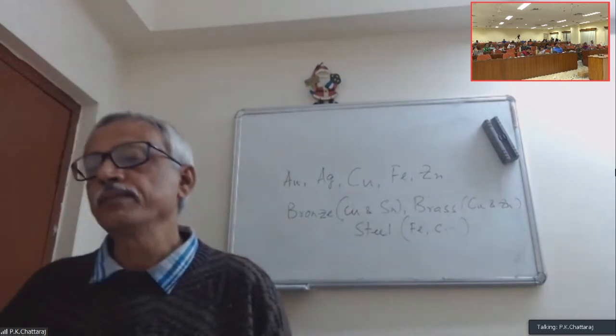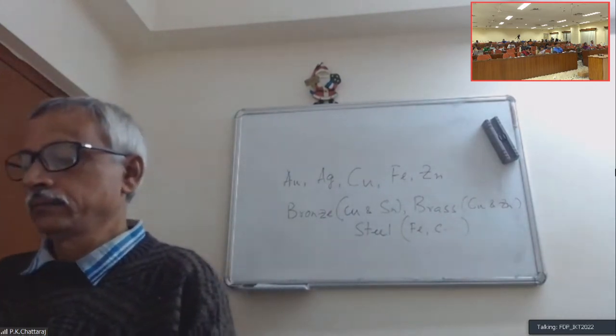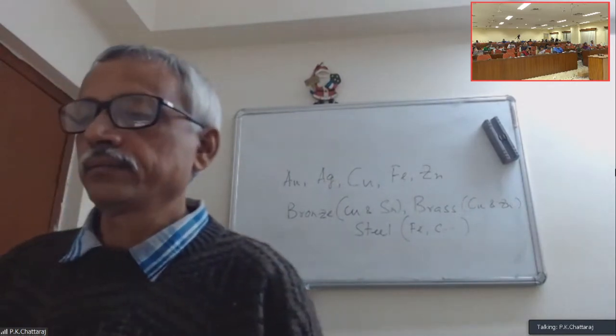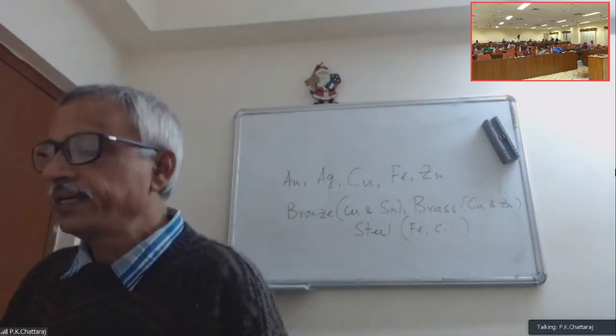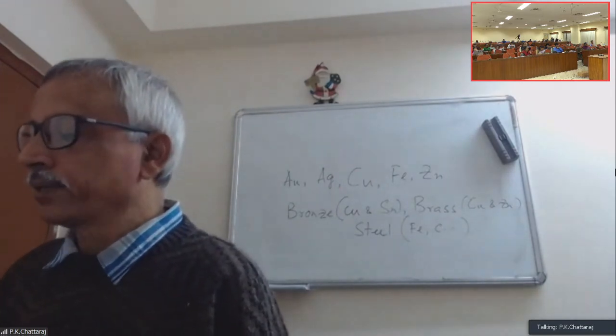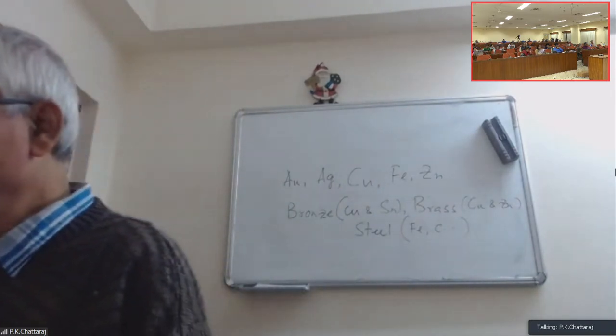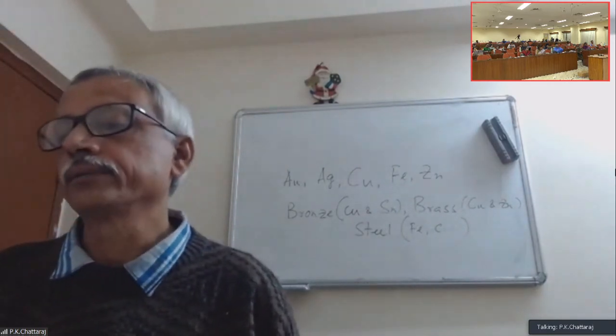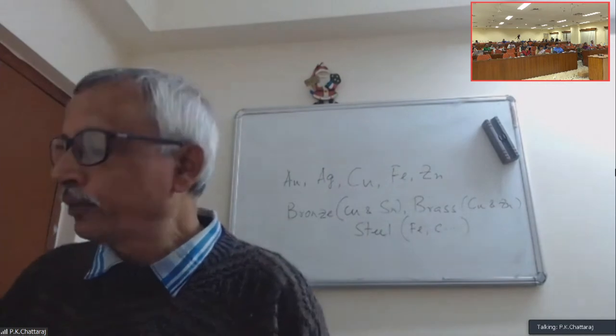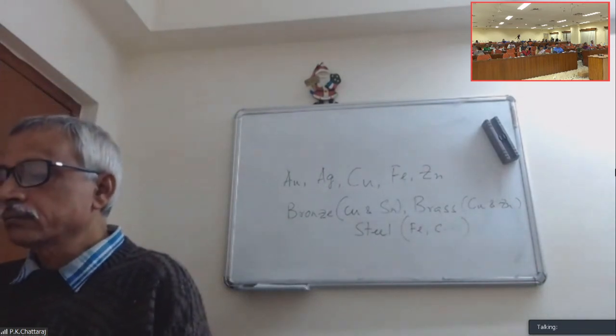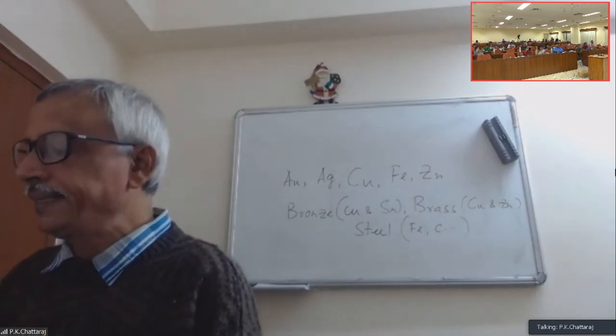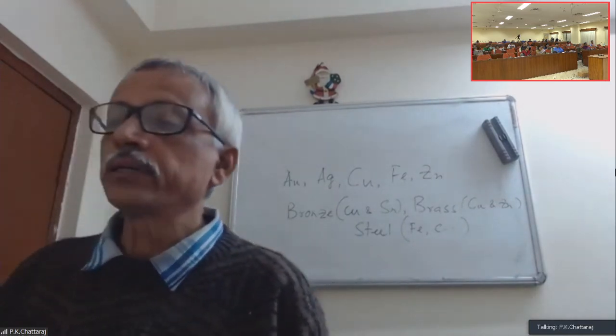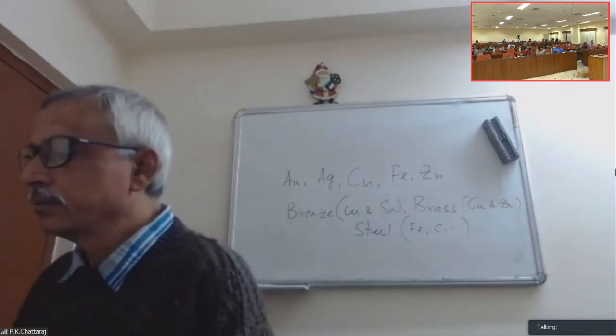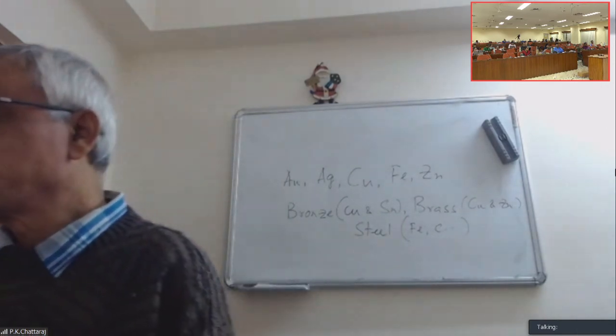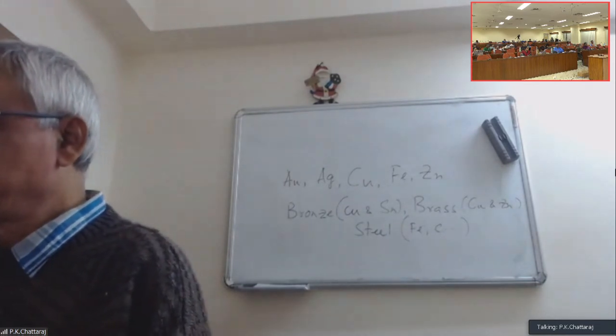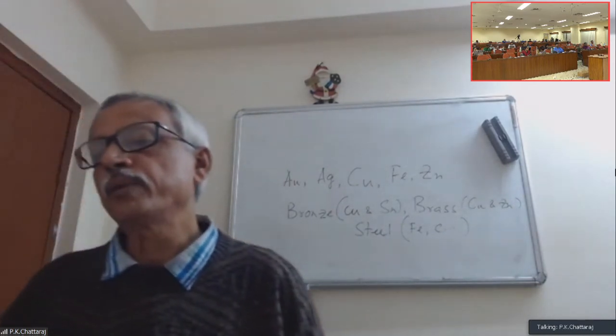But zinc metallurgy is not very simple like iron metallurgy. The boiling point of the zinc metal is at least 350 Kelvin lower than the minimum temperature required for the extraction of zinc from zinc oxide. So if you take the typical zinc oxide and heat it, by the time zinc oxide will melt and give you zinc metal, zinc metal will evaporate. So you can extract it only in the vapor form.